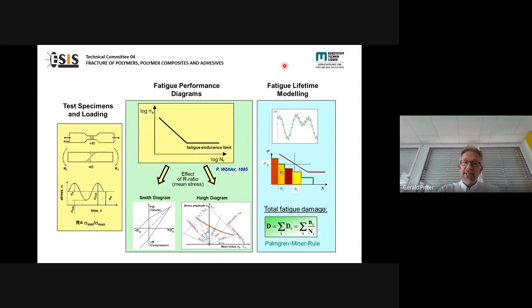And then there is even a possibility based on these S-N diagrams and these Wöhler lines to calculate the fatigue life, to do fatigue life modeling. And typically coming from metallic materials, this is done based on typical damage accumulation theories, like the Palmgren-Miner rule, where the damage is accumulated at the different testing levels. And in the end, you can really assess the lifetime, not only of specimens, but of course also of components. And in the end, I will also show you one case study dealing with this aspect for polymers and short fiber reinforced polymers. But this is the conventional aspect of dealing with fatigue in metals and materials.